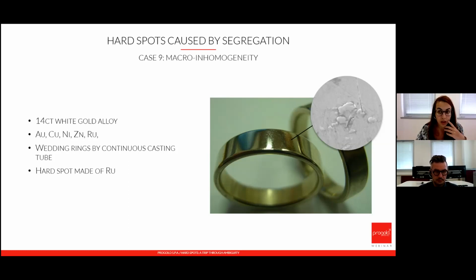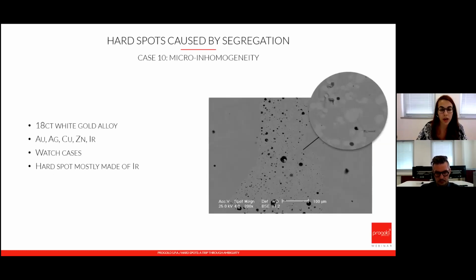As I said, this is also a typical grain refiner that was not mixed well enough inside a melt, and at some point they segregated because they were not soluble in the gold. In this case, we have the micro inhomogeneity, as this is also made out of an element that was already inside the alloy.